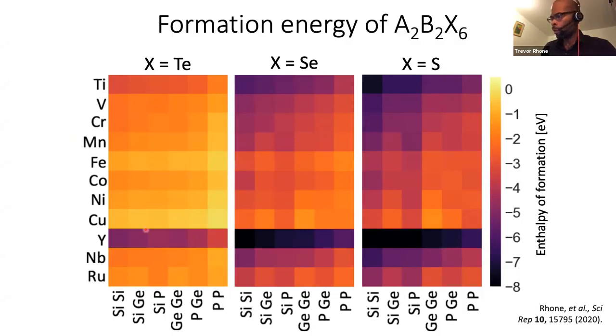Becomes less stable as the d orbitals, for instance in copper, get filled. And going from the second row from left to right of the transition metals, the trend is again holding. As you go up the column six from tellurium to sulfur, this is getting darker, which means that the chemical stability is getting stronger. Formation energy is getting more.